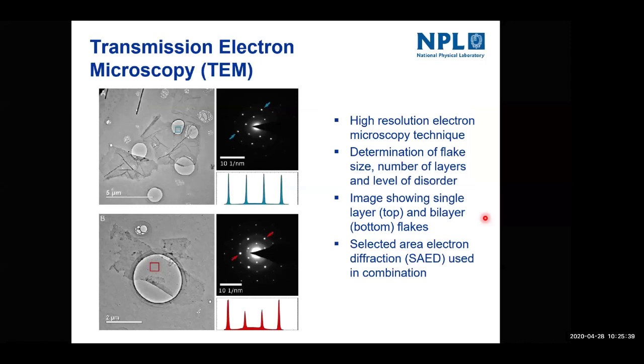So that's one way of looking at it through those selected techniques, but in the standard we also talk about TEM, which is transmission electron microscopy. Again, it's bombarding surfaces with electrons and looking at the scattered electrons, but it's a very high resolution technique. Typically, TEM is more expensive than the other techniques, it generally needs a higher level of expertise, and it's also quite difficult in terms of sample preparation. So there are those caveats with it, but it does give you a lot of information about these flakes.